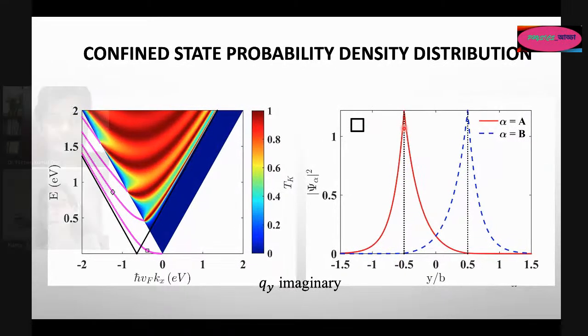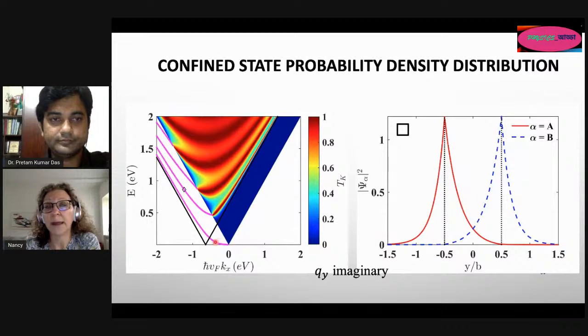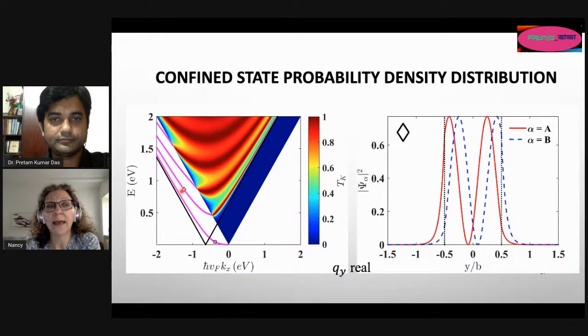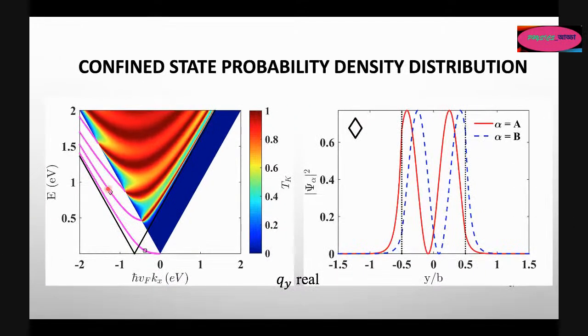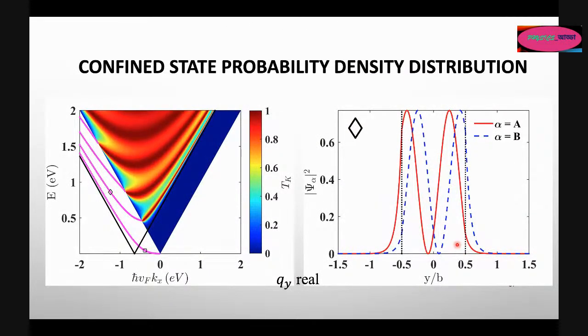These are the wave functions for the states located here, signaled by this square, and this is the wave function for the state that has this momentum and this energy. You see that the wave function of this state has an exponential decay outside and inside the barrier, and it's located precisely inside the barrier. This plot shows the state represented by this rhomboid here at this momentum and this energy, and the wave function also decays exponentially outside the barrier. It lives inside the barrier a little bit. It's not only at the edge, but these states are confined by the fold. So the fold has the same feature that it's able to localize states in the vicinities of its edges and inside the fold.